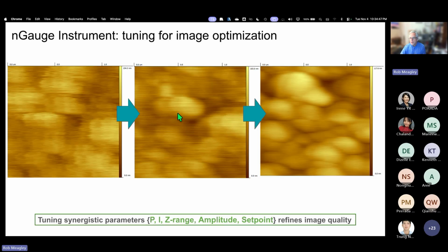Going from left to center, this was mostly optimizing P and I. And then as I realized that the surface had changed from the previous sample significantly, I went back, I reset the Z range to be a little bit more appropriate for the height. This is a sample that's giving me almost 200 nanometers of Z height. So I shifted the Z range a bit. I controlled the amplitude. I adjusted the set point so the tip was pressing a little bit harder. And then again, adjusting the P and the I iteratively brought in this beautiful resolution. And you can see that this coating has significant topology at about 5 nanometers or so. And a truly refined version of this image we'll see later.